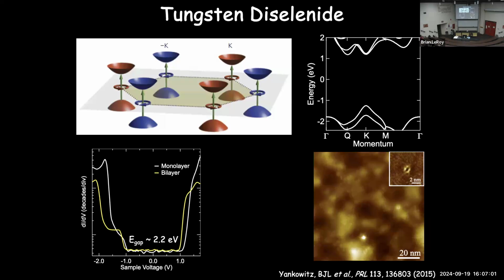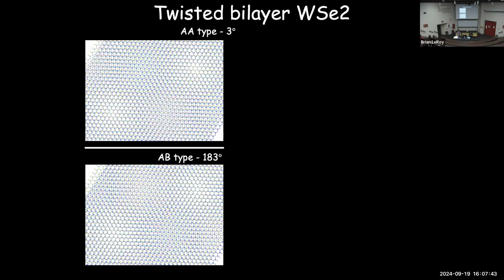In case you're not familiar with them, they are semiconductors with band gaps on the order of 1 to 2 electron volts. If we look at them here in monolayer and bilayer, we can measure the density of states as a function of voltage to probe the band gaps of these materials. In the monolayer, the white here, we have a gap of, I think it was 2.2 eV. When you create a bilayer, these bands slightly shift, and the gap reduces to about 2.1 eV. But there's not actually a significant change in the band gap as you add a second layer. But there is a significant difference in what the wave functions are going to look like.